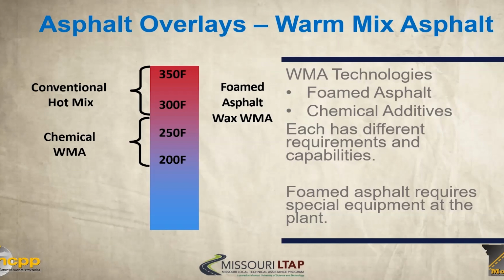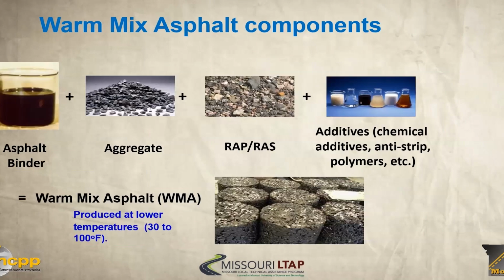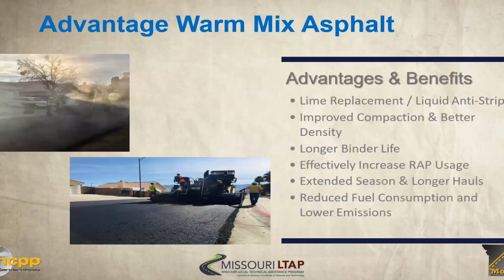Foamed asphalt requires special equipment at the plant. But if you look at the components, you have obviously the asphalt binder and aggregate, and then you could have RAP or RAS, and then the additives. If it's a chemical additive or antistrip, polymers, those types of things. And you add all those things together and you get warm mix asphalt, which is typically produced at much lower temperatures, meaning less greenhouse gas emissions, less fuel burned at the asphalt plant.